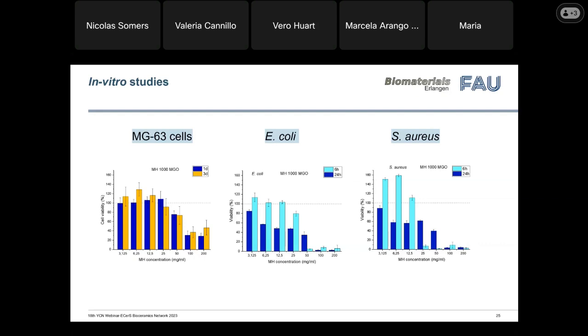So here we have some results of this experiment. Different concentrations of Manuka honey were tested, and the same concentrations were used for both studies. We can see that for the cells, our limit was around 50 milligrams per milliliter, but for the bacteria, we found that after 24 hours, even a lower amount was toxic to them. So this was quite useful for us to keep investigating on this topic.